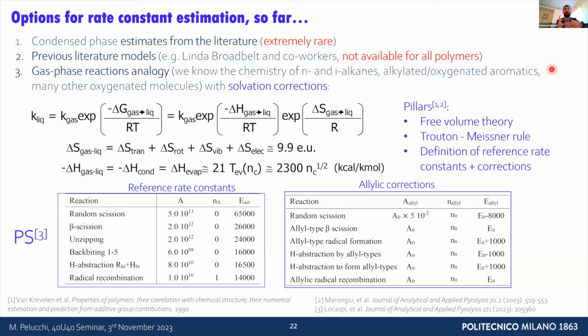You can make gas phase reaction analogy. We know the chemistry of N and isoalkanes, alkylated and oxygenated aromatics, many other oxygenated molecules. If we take into account the solvation correction, so we transpose that from the gas phase to the liquid phase, and the pillars in these are the free volume theory, Trouton-Meissner rule, we can define reference rate constant and corrections.